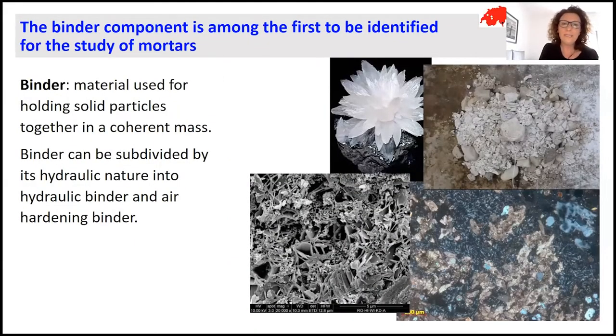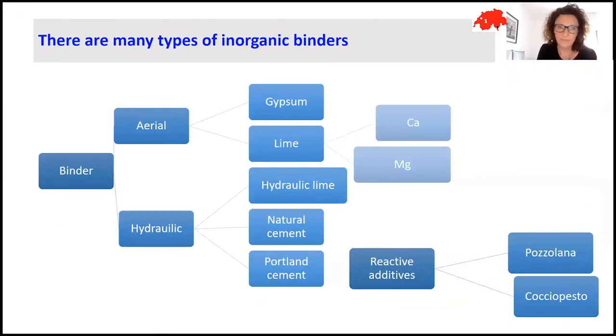The binder component is the first thing that normally should be identified while studying a mortar. An important classification of the binder is to understand if it is an air hardening binder or a hydraulic binder. We can have different binders that can be used. For example, the air hardening ones are gypsum and lime. Then we have the hydraulic ones, and we also have different possibilities. In this case, we have natural hydraulic lime, artificial hydraulic lime, natural cement, or Portland cement.